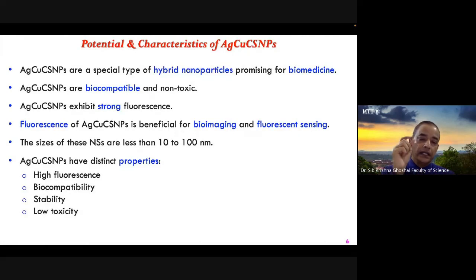So the size of this nano core-shell structure or nanoparticles, in general nanotechnology, we say 10 to 100 nanometer, but the nanoparticles we produce are from 5 to 25 nanometer mostly. So they are very effective for this application. They have high fluorescence, they are biocompatible, they are stable, and they are low toxic.